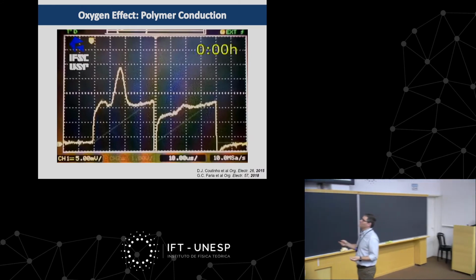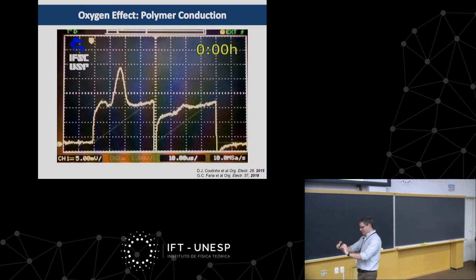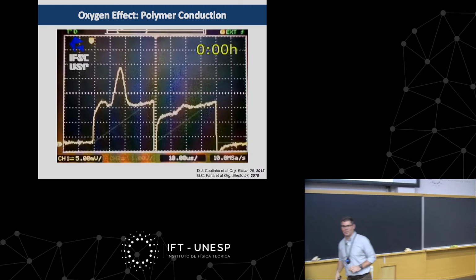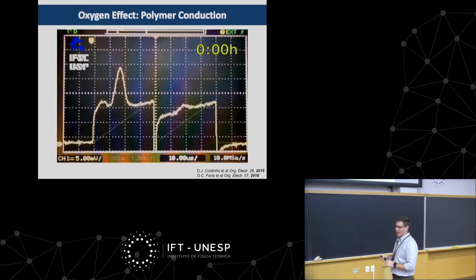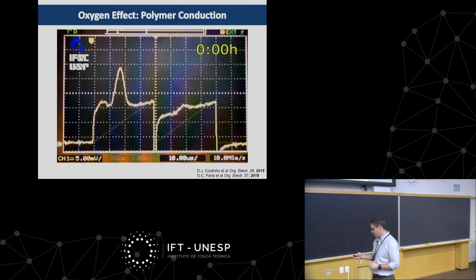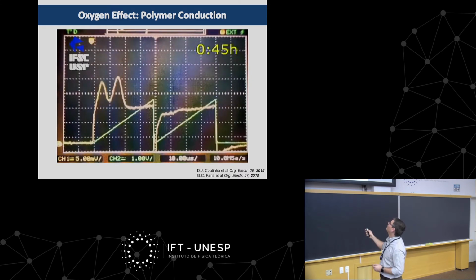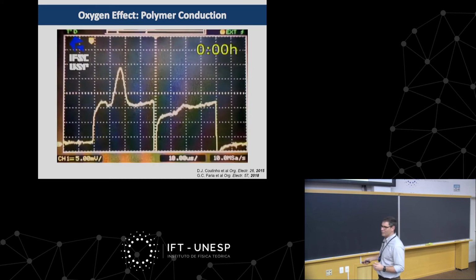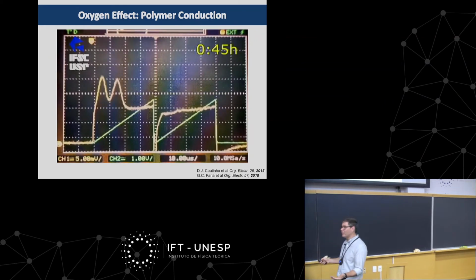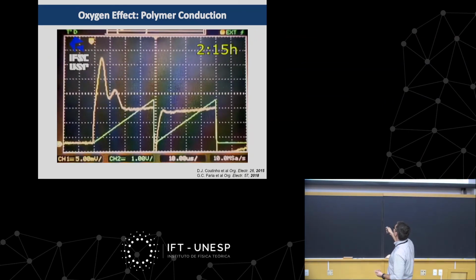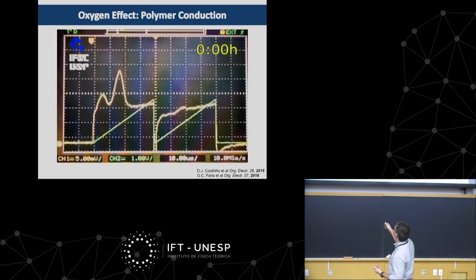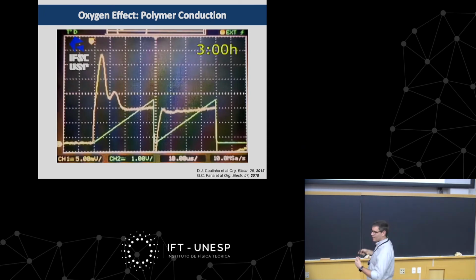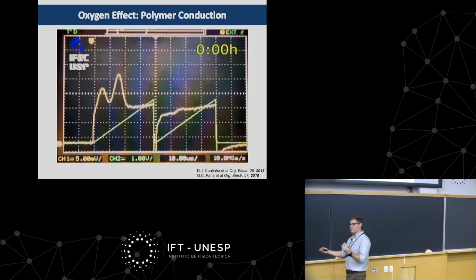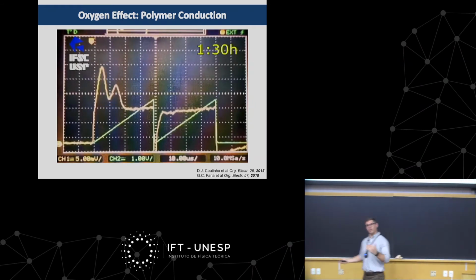And what we did, we put a small little camera focused on the screen of that particular oscilloscope, and we let the time of exposure go on. And this is basically what happened. As the time of exposure to oxygen goes on, you clearly see a transition between two different modes of conductivity. First, charges were in the middle, and as time evolves, this charge actually gets reduced. You see that this peak is being reduced, and this one gets increased. So you clearly have extraction of different types of charges going on in that particular material.